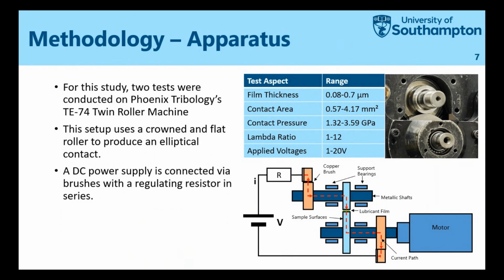And we spin them, for this test, in PAO8 oil. It's just base oil, which creates a nice lubricated contact. With the T74 and these samples, we can produce a range of film thicknesses, contact areas, and contact pressures, which gives us enough scope to test all the lubrication regimes and give a nice variation in electrical behavior. With that, we hook up a DC supply with a regulating resistor in series to regulate the amount of current passing through the contact.